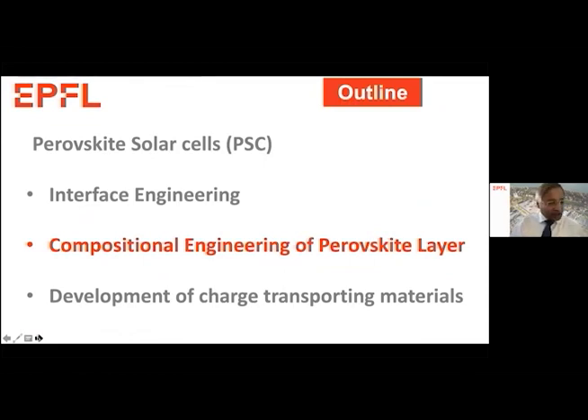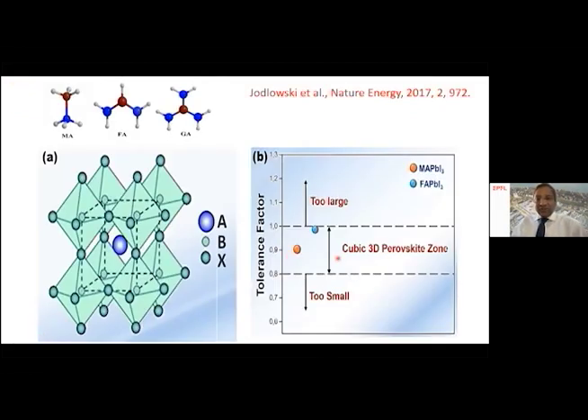Now I come to the composition engineering of the perovskite solar cells. If you look at the various cations on the top left side of the screen, you see methylammonium, you see formamidinium in the middle, and you see the guanidinium. Guanidinium has a carbon and three amino groups. But if you look at the size of these cations and the formation of the cubic structure of perovskites shown here, if the tolerance factor is within the range between 0.8 to 1, then the probability of forming cubic 3D perovskite is extremely high. If the cation is too large, it will not form the three-dimensional perovskite. If it's too small, it doesn't form the perovskite either.